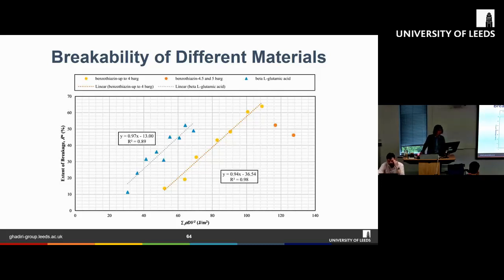You can see that here we have beta L-glutamic acid, and you can see that they are nicely lined up. Basically, we have this linear correlation, and then compared to benzothiazine, you can see that the slope of this line represents how breakable the material is. So here benzothiazine actually has a lower breakability index as compared to beta L-glutamic acid.